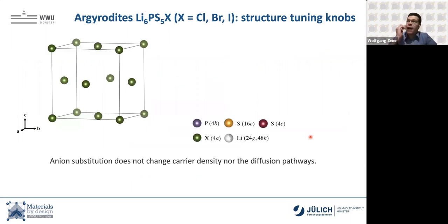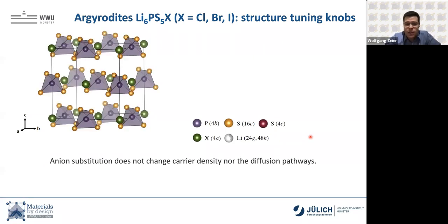All right, in the first part, we'll talk about the so-called argyrodites, the lithium thiophosphates, so Li6PS5X. And this X is a halide, so a chloride, a bromide, or an iodide anion. The halide forms an FCC lattice, and you have these ortho-thiophosphate PS4 3- tetrahedra pretty much sitting on the octahedral sites. And then you have a free sulfur S2- anion that's in half of the tetrahedral holes.